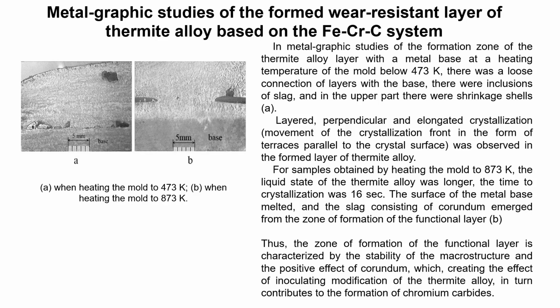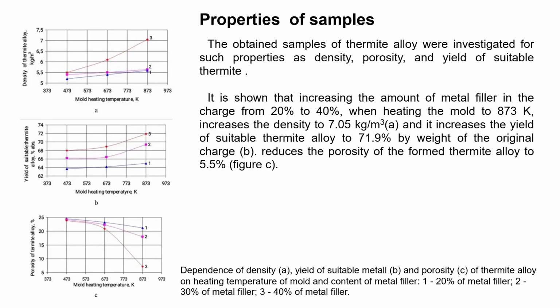Thus, the zone of formation of the functional layer is characterized by stability of the macrostructure and the positive effect of corundum, which creates the effect of inoculating modification for the thermite alloy, in turn contributing to the formation of chromium carbides. The obtained samples were investigated for such properties as density, porosity, and yield of alloy.